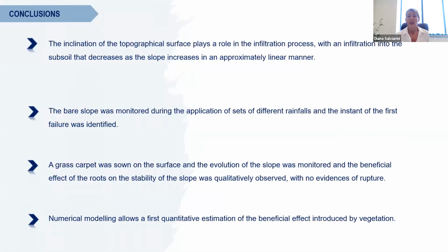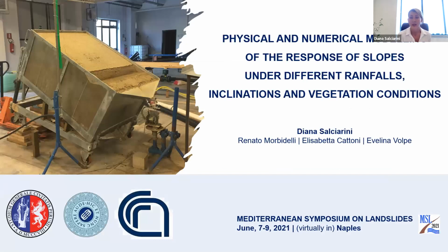So coming to the conclusion, we observe that the inclination of the topographical surface plays a role in the infiltration process, with infiltration into the subsoil decreasing as the slope increases in an approximately linear manner. The bare slope was monitored with the aim of recording the instant of failure. Then a grass carpet was sown on the surface, and the evolution of the slope was monitored, and the beneficial effect of the roots was qualitatively observed. And finally, we tried to quantitatively estimate the beneficial effect exerted by the roots with a numerical model taking into account the mechanical improvement. Thank you for your attention.